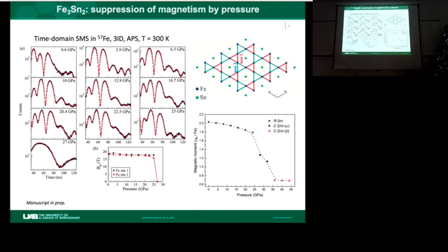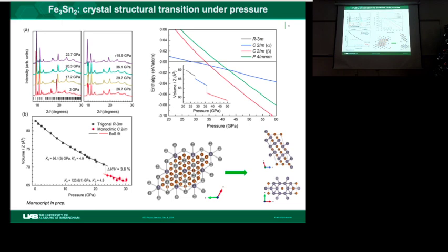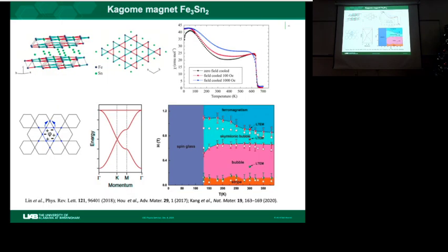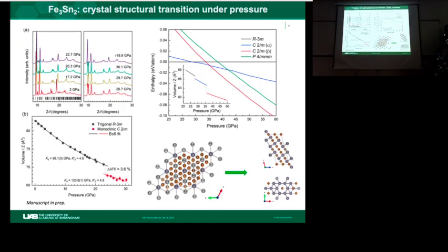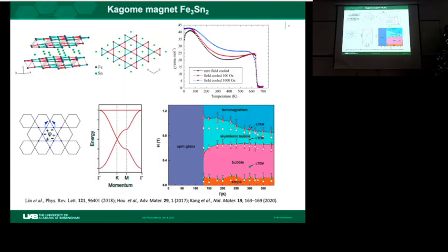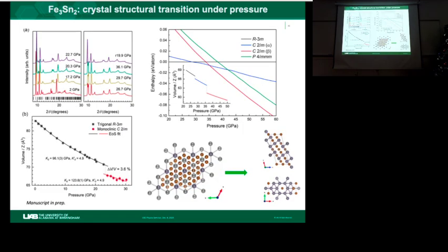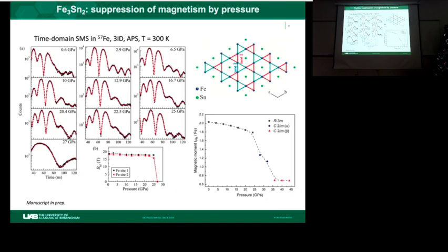In this case, this Kagome lattice is basically a special arrangement of atoms, and because of electronic destructive interference, you have a flat band near the Fermi level. In this specific case, we actually have two types of bonding between the ions, and these two bonds vary very slightly, by less than 1% difference in bond length, but we can actually sense that using the Mössbauer effect.